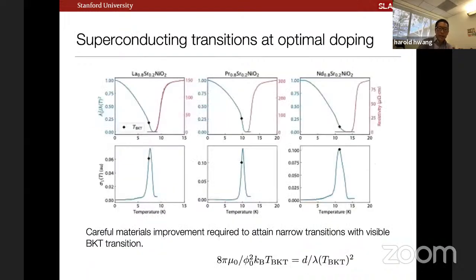Okay, so what does the basic data look like? I'm looking just now at the optimally doped compounds for the 3 different families of the infinite layer phase, so lanthanum, praseodymium, and neodymium. What I'm plotting here is 1 over lambda squared, essentially, at the onset of superconductivity. And what we generically see is quite familiar from other thin film measurements of this sort: we see the onset of superfluid density after we've reached a resistive zero.